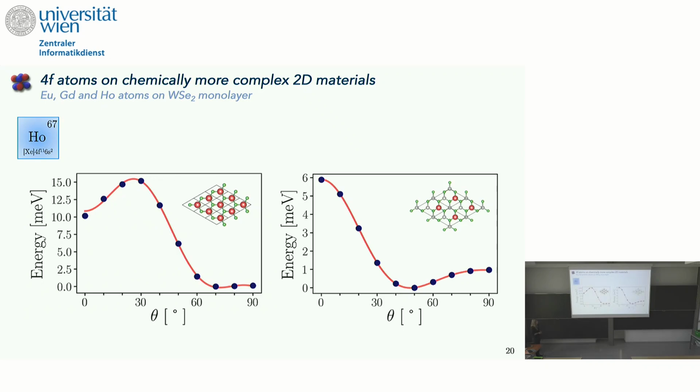If we have a look at holmium, which chemically behaves similarly to europium, we don't have the outside 5d electron. We have the same trend. So a larger magnetic anisotropy in the full coverage situation and a smaller magnetic anisotropy when it's diluted. And well, overall, of course, these magnetic anisotropies are much larger compared to the half-filled 4f shells because, I mean, it's an open 4f shell with strong spin-orbit coupling. We also have kind of to consider the fact that these open 4f shells contribute to the crystal field. So there's kind of like a 4f repulsion, which is much smaller in gadolinium and europium.